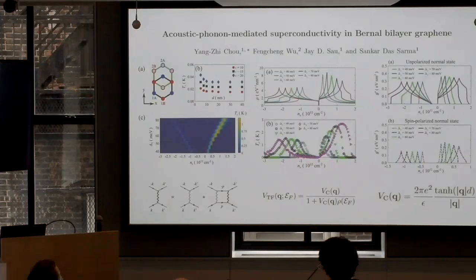Here, the most important take-home message: TC is very low. Look at TC. It's on the order of 20 millikelvin. Before it was like 1 to 2 Kelvin. This is good because things should depend very strongly on band structure. And the band structure changes completely.